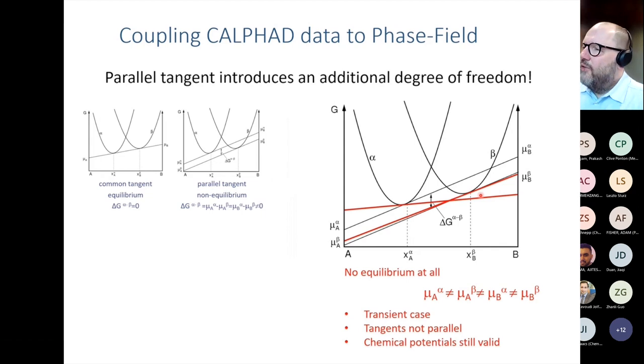So, but what happens now if we go off equilibrium? If we're off equilibrium, we release that constraint of parallel tangents. We assume that a phase is at any given composition, somewhat, I nearly said randomly, but somewhat arriving at the composition. It doesn't matter how the phase gets there, but somehow some composition of a phase. And that forms a tangent. And if we form a tangent to that phase, we can then determine the corresponding chemical potentials. But there isn't a clear rule between that. So we find that how the chemical potentials between the two phases and the two elements actually relate or do not relate, there's even a change in sign. If we take the difference between this and this one compared to the chemical potentials over here, one has a positive sign, the other has a negative sign. And definitely there's no equal chemical potentials in that.